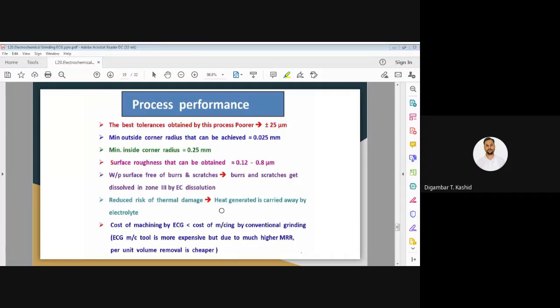Then there is the process performance. The best tolerance obtained by this process is plus or minus 25 micron. The minimum outside corner radius is 0.025 mm, and the minimum inner corner radius is 0.25 mm. Again, the surface roughness that can be obtained using this electrochemical grinding process is 0.12 to 0.8 micron.